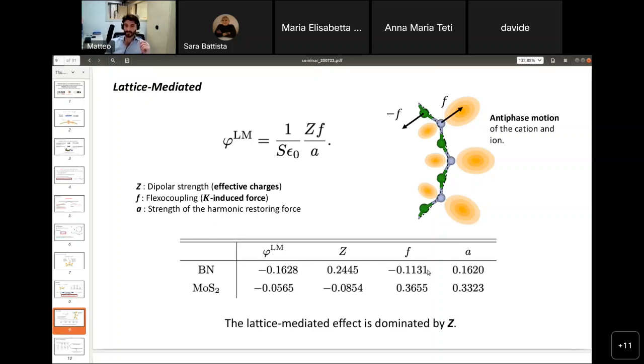Remarkably, for the systems considered, we find that the ratio between F and A is always more or less the same. And so we can say that the lattice-mediated effect is largely dominated by the effective charges. This can help in a hypothetical material design.